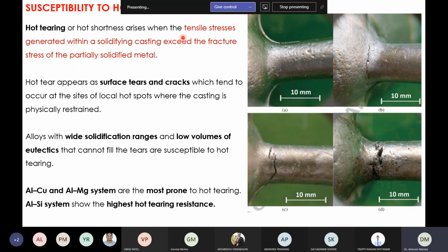These cracks occur when the tensile stresses generated within the solidifying casting exceed the fracture stress of the partially solidified metal. This is one theory which tells why these particular cracks are generally visible in many castings, again at certain locations only. This phenomenon is called hot tearing, because it occurs during the solidification process in the hot condition itself. It's not anything after that. This is one of the reasons by which hot tears appear in your castings, and mostly these are surface cracks, which you can see.